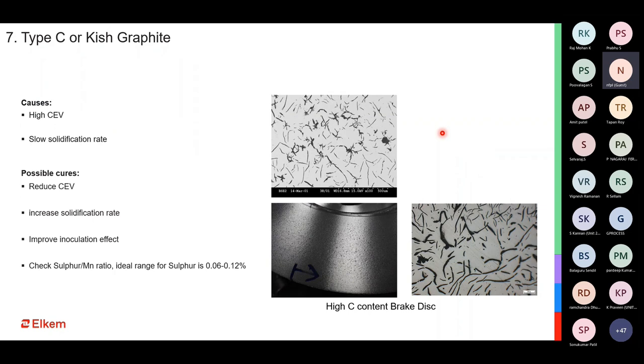The other aspect of graphitization is the type C graphite, that is the Kish graphite. Kish graphites are coarse graphite flakes, like the one that you see here. These are very heavy and thick graphite flakes, visible in the casting mostly when you have a very slow solidification rate, due to which the carbon segregates in one or a few locations. And also when you have a very high carbon equivalent. When you have a high carbon equivalent, the carbon has to go somewhere, right? So it tries to accumulate and agglomerate at a particular location, thereby increasing the thickness of these graphite flakes.